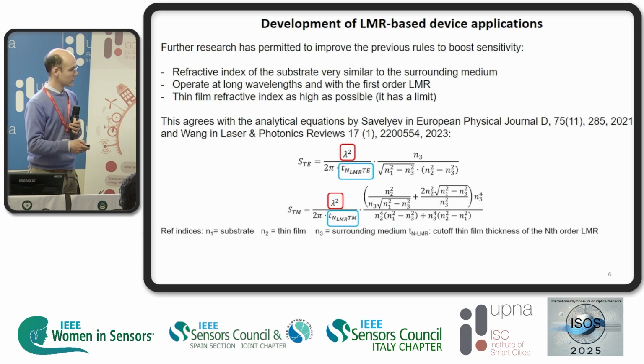In addition, the other parameter to consider is the cutoff thickness of the lossy mode resonance. The thickness for generating the LMR rules also the sensitivity. That is why with lower order LMRs obtained with thinner coatings, we get a better sensitivity. So these two parameters are fundamental. And also, as I said to you before, the thin film refractive index as high as possible, but it is not so easy to observe it here. If we solve these equations and plot them as a function of N2, we observe that there is a high growth as we increase the thin film, but later it saturates.